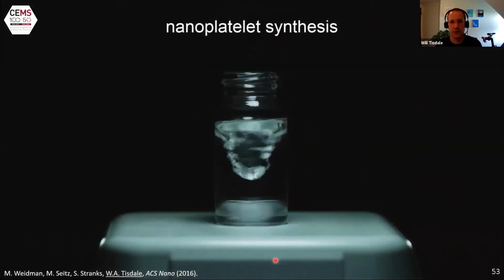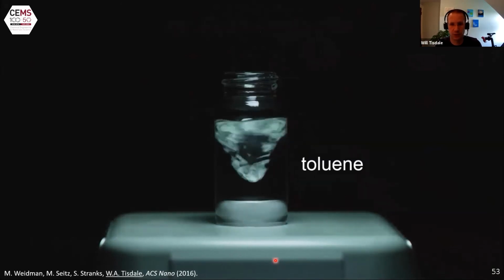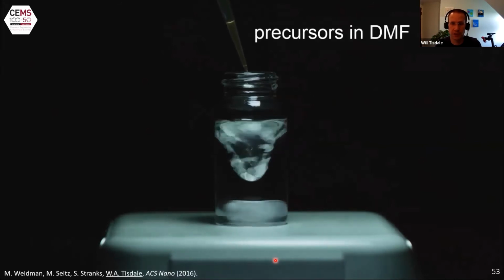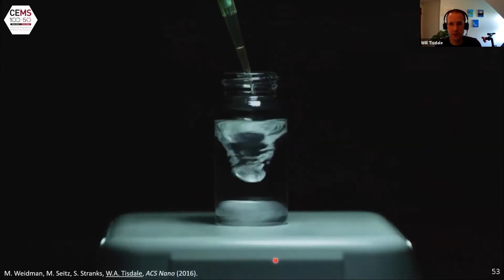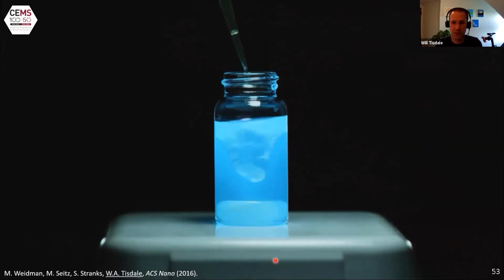This is a video of that synthesis. This is just pure toluene, room temperature in the fume hood on the bench top. And these are the precursors dissolved in dimethylformamide along with some surfactant. And you simply drop them in and you instantaneously get this blue emitting structure.